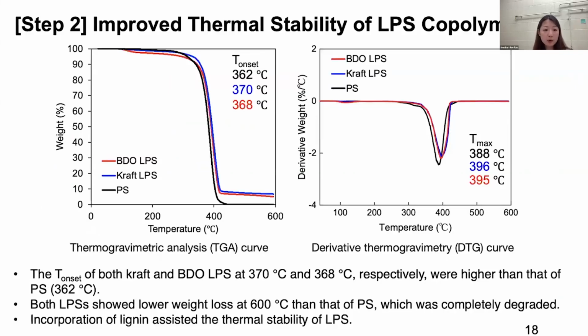The thermal properties are very important for polymer material. So we measured the thermal stability of the LPS copolymer. The polystyrene showed 360 degrees Celsius, and once we introduced lignin into the LPS copolymer system, both BDO and Kraft LPS increased, so that the BDO LPS showed 368 degrees Celsius and Kraft lignin 370 degrees Celsius. The maximum degradation temperature also shows that the incorporation of lignin improved the thermal stability of the polymer system compared to polystyrene itself.